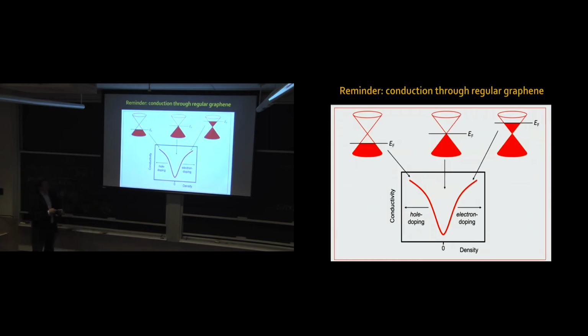So now let me remind you how graphene conducts. You measure the conductivity of regular graphene as a function of density. If your Fermi energy is deep in the valence band, you have lots of holes, so you conduct well. If it's deep in the conduction band, you have lots of electrons, so you conduct very well. If your Fermi energy is at the Dirac point, you don't have much charge carrier, so you conduct poorly. So graphene conductivity versus density has this V-shape, and this has been seen by thousands of groups.